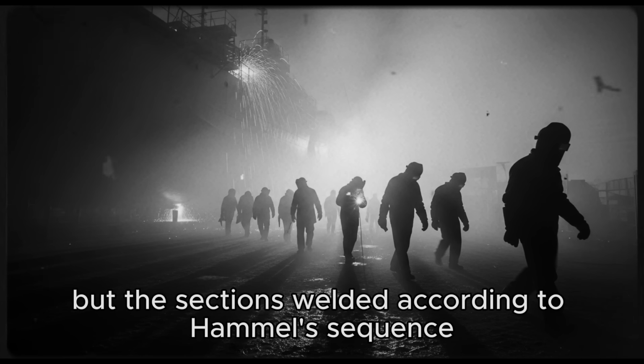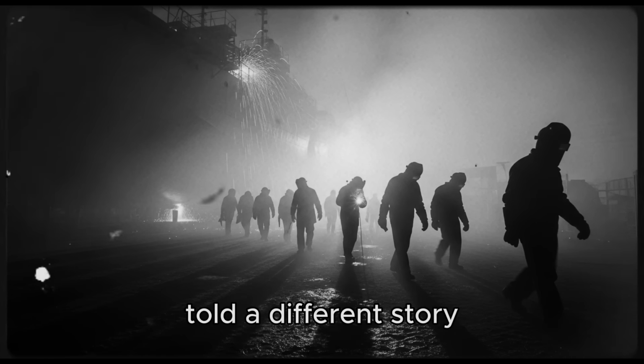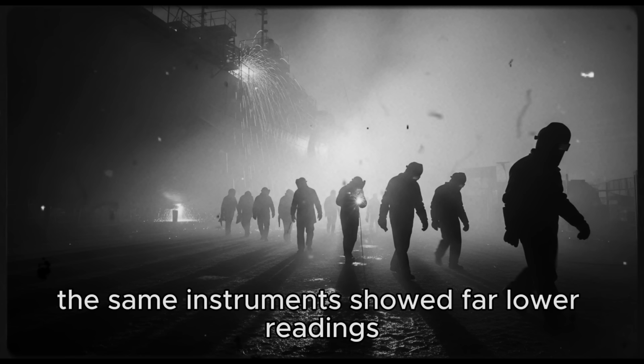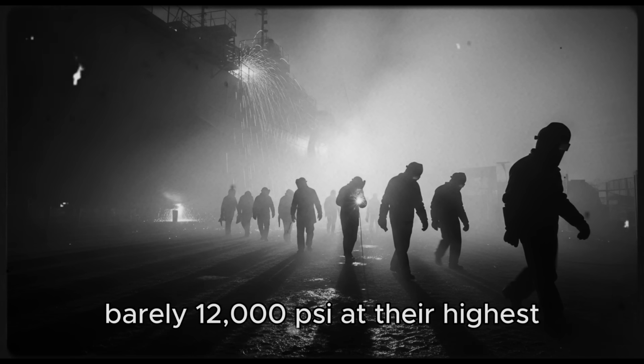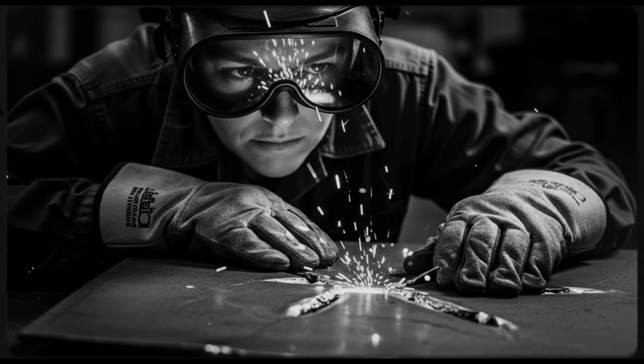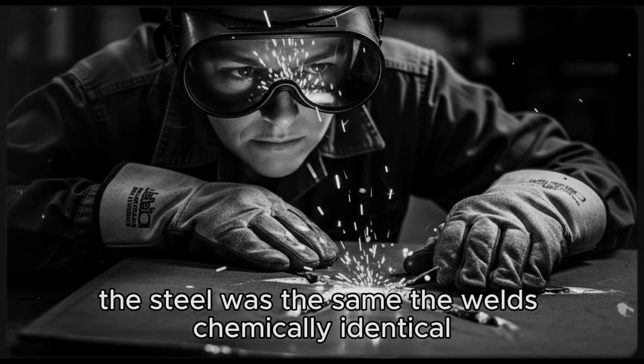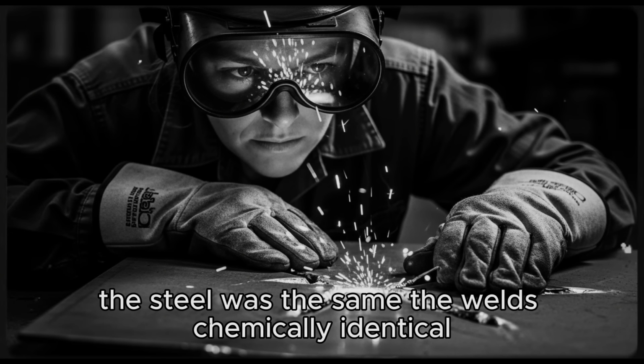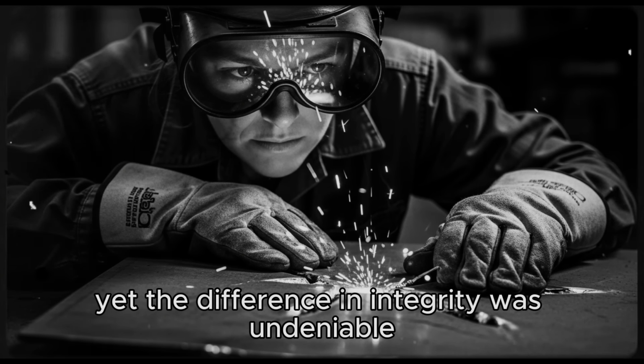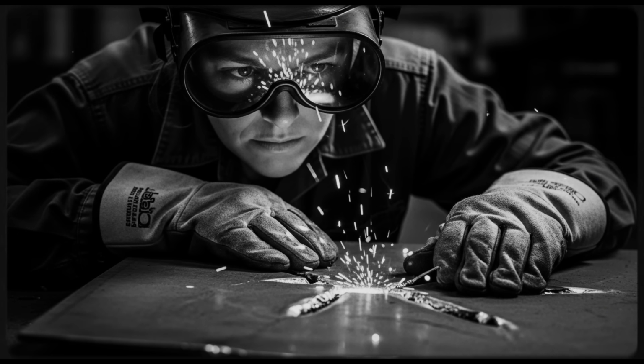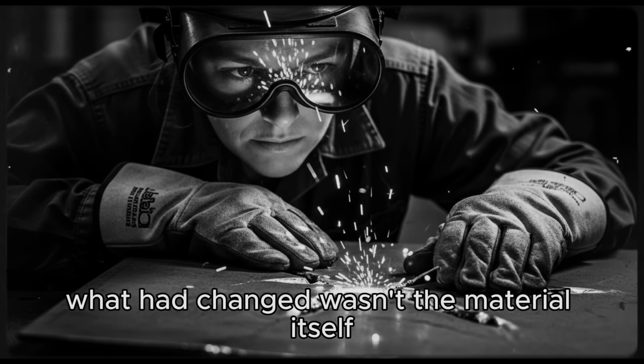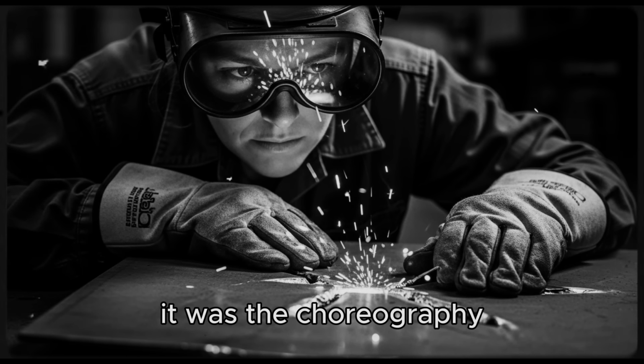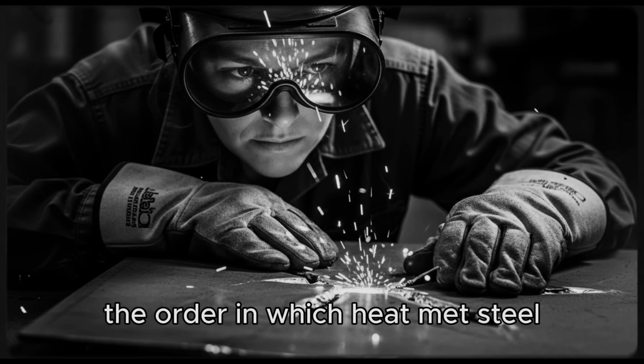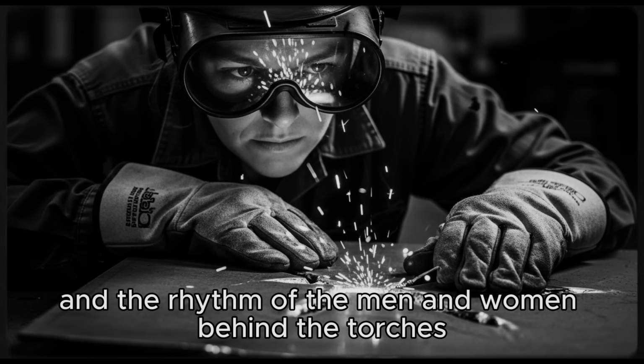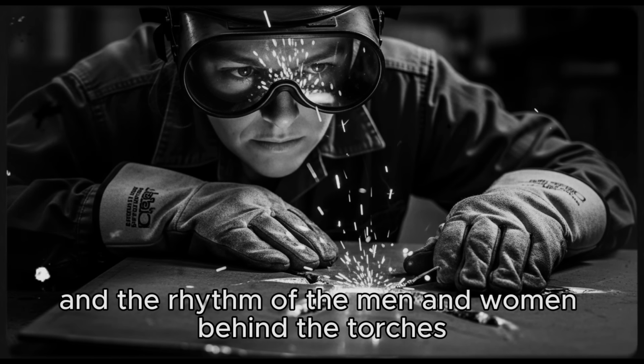But the sections welded according to Hammel's sequence told a different story. The same instruments showed far lower readings, barely 12,000 psi at their highest. The steel was the same, the welds chemically identical, yet the difference in integrity was undeniable. What had changed wasn't the material itself. It was the choreography, the order in which heat met steel, and the rhythm of the men and women behind the torches.